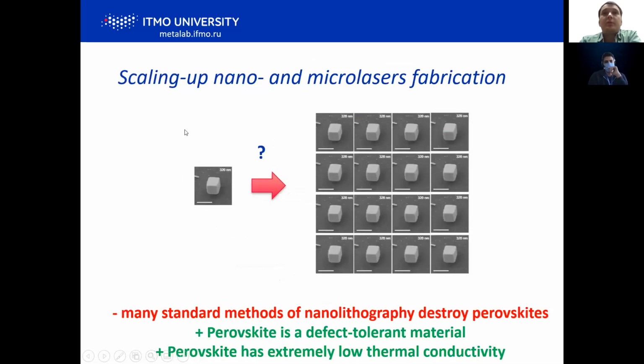And in the last part of my talk, I will discuss how we can scale up nano and micro laser fabrication, because many standard methods of nanolithography are not suitable for perovskites because they don't like polar liquids. So all these methods should be applied with care. On the other hand, laser nanostructuring is quite a clean method, because it is just heating by photons, no chemistry. And perovskite, as I already told, is a defect-tolerant material, so it's quite robust to defects, and it has very low thermal conductivity.